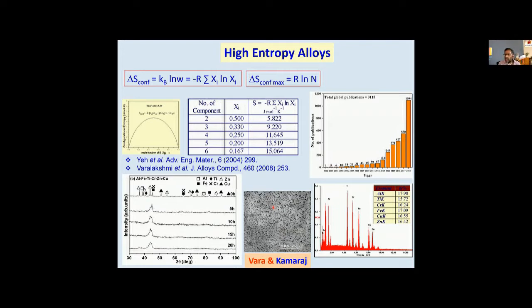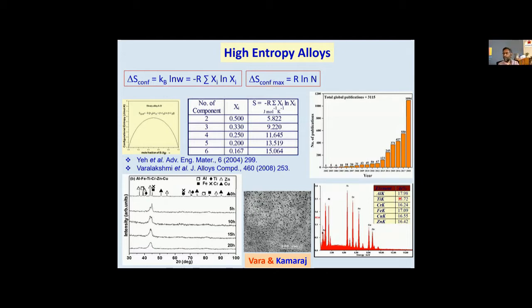For these 10 to 20 nanometer particles, to know the composition we use something called EDS — energy dispersive spectroscopy. I can put an electron beam on this particle and get to know the composition. When we did that, we saw that each of the six elements was very close to 16.5 plus or minus 1%, telling you that every particle is uniform in composition and has the equiatomic nature — equal amounts of all elements. We are able to make nano high entropy alloy particles, and when we look at their mechanical properties, they are shown to be exceedingly good.